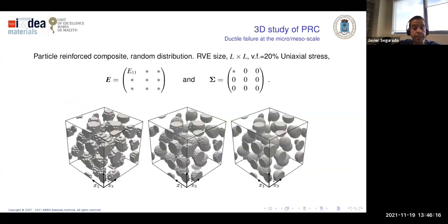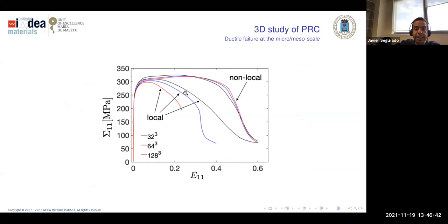This is checked in 2D, and we can check it in 3D, but for a more complicated RVE. So for a real material reinforced with spherical particles, and not only one in the middle, so not periodic, but a random arrangement of them. Now let's apply some uniaxial strain in one direction, and let's see what we get. The first thing that we get is that if we use, in this framework, local plasticity, local Gurson, sorry, we have a strong voxel size effect, as it happened in FE.